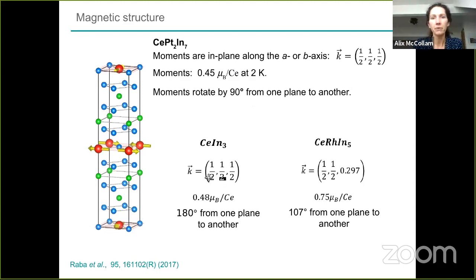Comparing that with cerium indium-3, the ordering is similar. It's half, half, half also in cerium indium-3, with a similar Bohr magneton per cerium atom. And then the rotation in this case is 180 degrees from one plane to another. So that's from one cerium indium-3 plane to another. And that's also what I mean here. The moments rotate from one cerium indium-3 plane to the next cerium indium-3 plane.